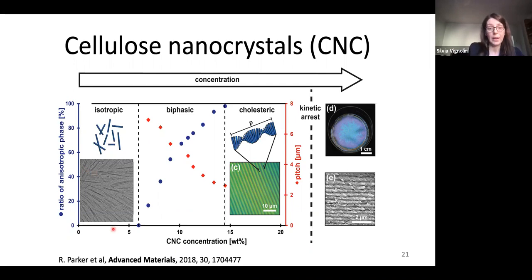So when we evaporate water, we increase the concentration of this cholesteric structure, and what is happening is that before, they are dispersed in water, so they don't interact, and their distribution is random inside the suspension. But then as soon as you increase the concentration, they start to feel each other, so they start to interact, and what they do, they start to form this cholesteric structure. And if you remember a few slides before, they create this layered architecture that is really similar to what I've shown you in the case of the fruits.